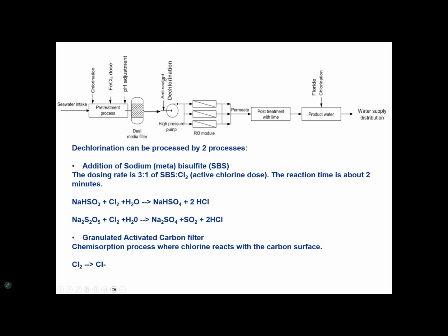Nowadays, because of the brine mining purpose, nanofiltration is utilized. Nanofiltration is basically similar to a polyamide membrane, and this also has very weak oxidant tolerance, so dechlorination is necessary. But microfiltration and ultrafiltration, which are basically PVDF or PP membranes, have a very high tolerance of chlorine.